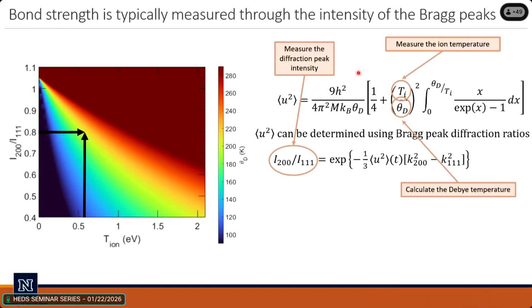What we have, though, is we can do the same experiment. So we've got this massive equation I showed earlier. Essentially, if you measure the ion temperature and the diffraction peaks, you can pull out the Debye temperature. For those of you in the know, this is Debye-Waller theory. This says the diffraction peak strength is related to the vibration of the atoms. So if the atoms vibrate more around the lattice sites, the diffraction peaks go down. If they're strongly in the lattice sites, the diffraction peak intensity will go up. And if you combine that with a measurement of the ion temperature, which you see here, then you can directly measure the Debye temperature with no approximations whatsoever. So I know exactly how strong my bonds are.